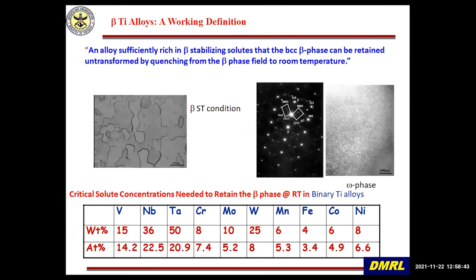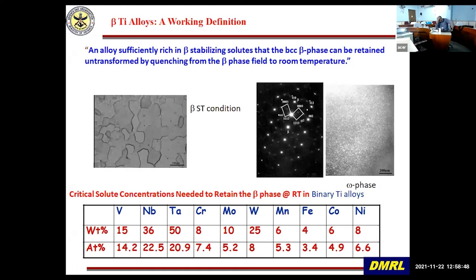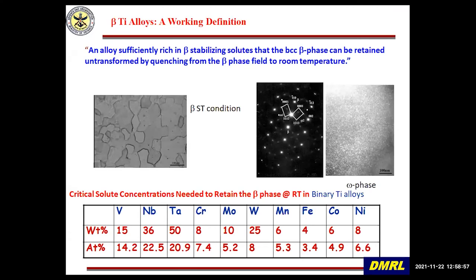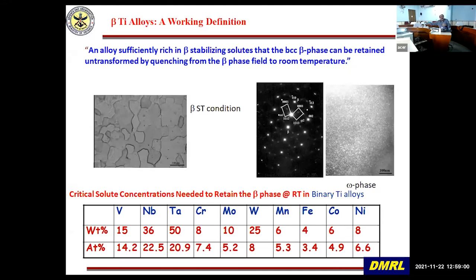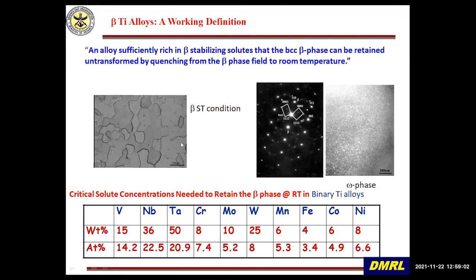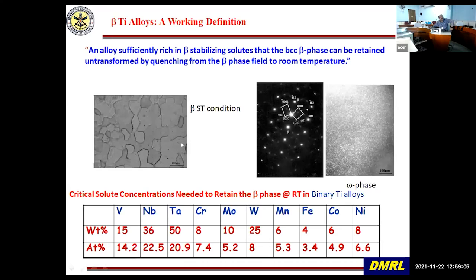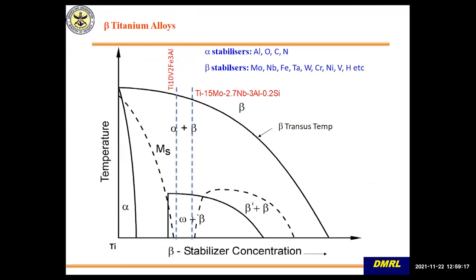Then coming toward the end, I will just come to beta titanium alloys, which are high strength titanium alloys, mainly used for strength applications. Now, what are beta alloys? Beta alloys are alloys in which you have sufficient beta stabilizer content, and you can retain the beta phase by cooling at faster rates. Then when you age, you get very fine precipitation of alpha and thereby higher strength. Mind you, these are not for high temperature application, but for strength applications.